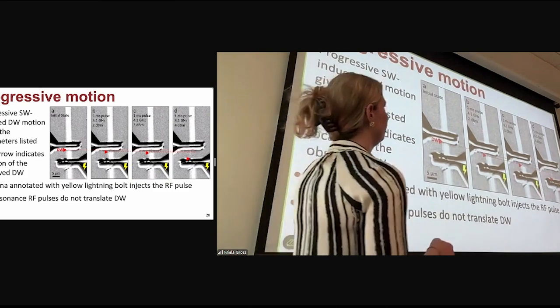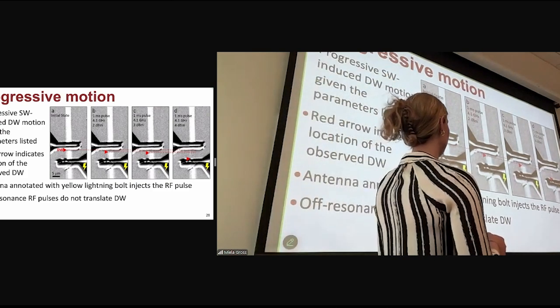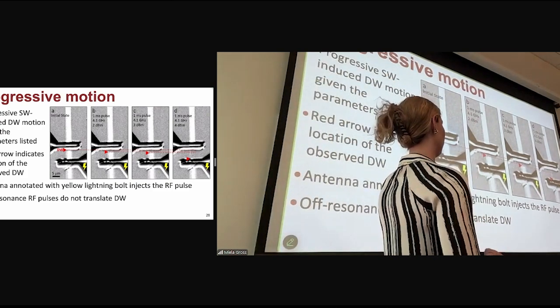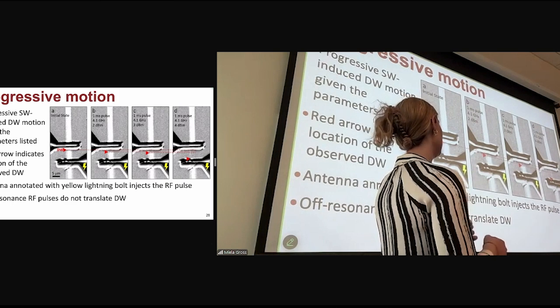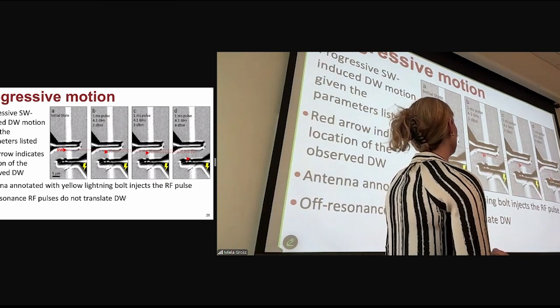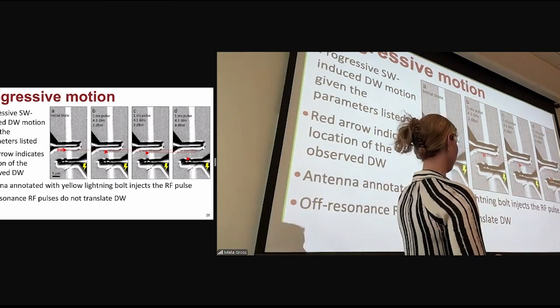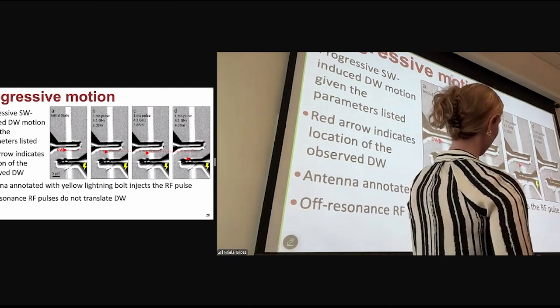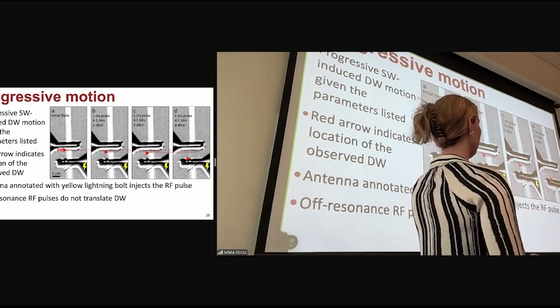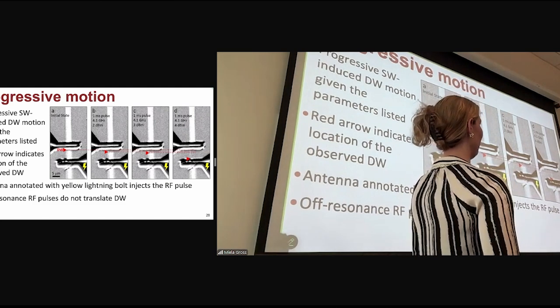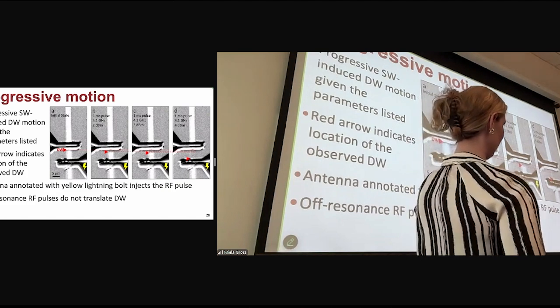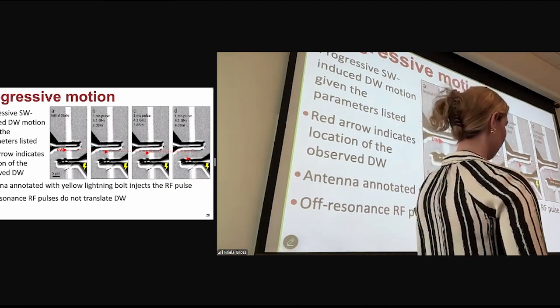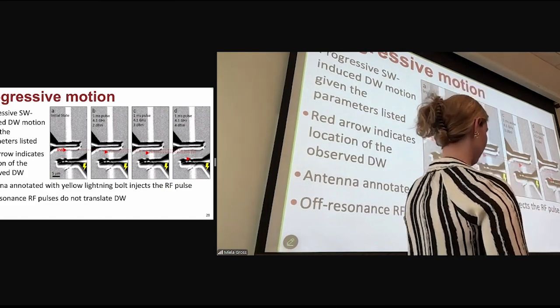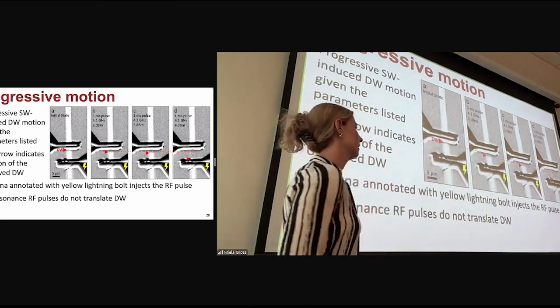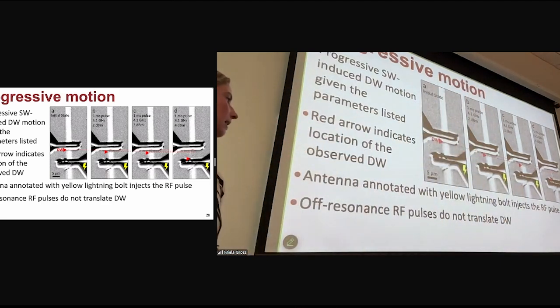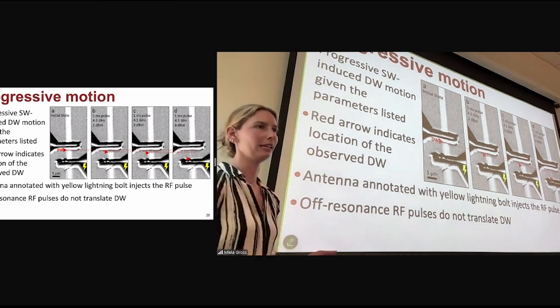After an RF pulse of 1 millisecond, around 4.1 gigahertz, which is near resonance for this bismuth device, we see the domain wall move a couple microns towards the injector source. A sequential RF pulse at a slightly increased power moves it another micron, and then a third pulse, again at increased power, moves it the remaining 7 microns towards the injector antenna. We repeat these experiments with off-resonance RF pulses, and we don't see any domain wall motion.